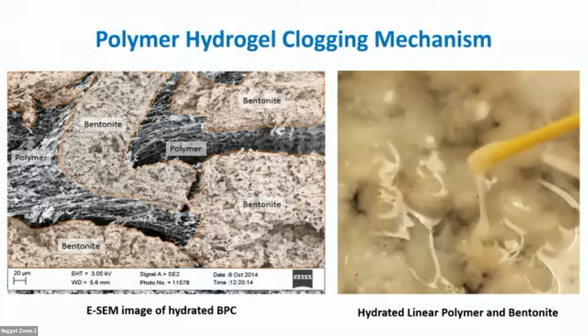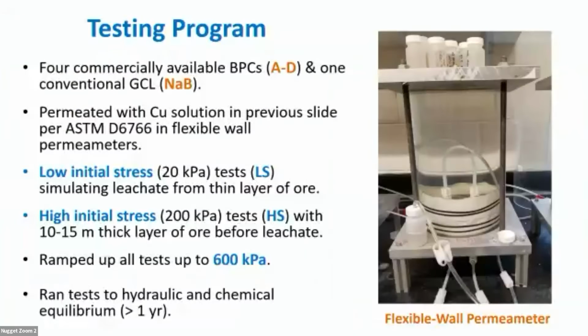This is what these materials look like when they hydrate. This is an environmental SEM on the left, or a wet scanning electron micrograph. You can see the bentonite granules here that have hydrated, and then you can see the polymer that's bridging and filling the pores between them. And on the right, you can see a photograph of this gooey, sticky stuff. That's the hydrated linear polymer with the gray bentonite in the background, or partially swollen bentonite granules. And it's really this clogging of the polymer filling those voids that makes these materials impermeable.